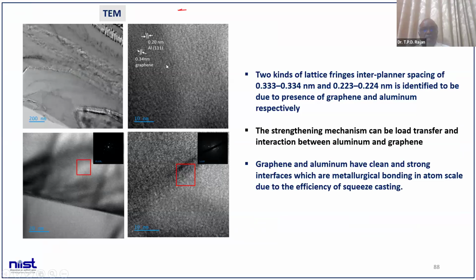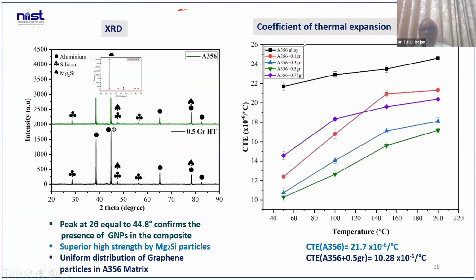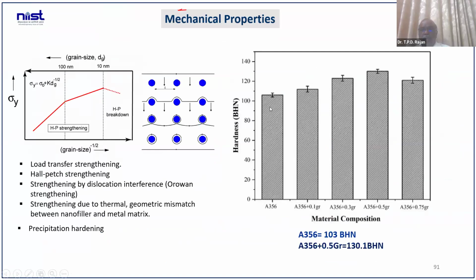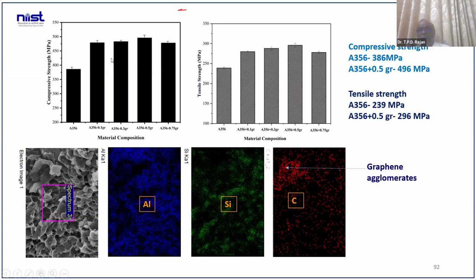So these are all the aluminum graphene TEM studies, which show the bonding is perfect. And the CTE, the coefficient of thermal expansion, is also getting reduced from 21.7 to 10.28. The mechanical properties increased, especially the hardness from 103 BHN to mostly 125, 130 BHN. This 103 for 356 alloy and 130 for this one. That is for the graphene composites. Again, the compressive strength for A356 alloy is 386, and this is getting increased to almost 496 megapascal, and the tensile strength from 239 to 296 megapascal by the addition of 0.5 graphene.